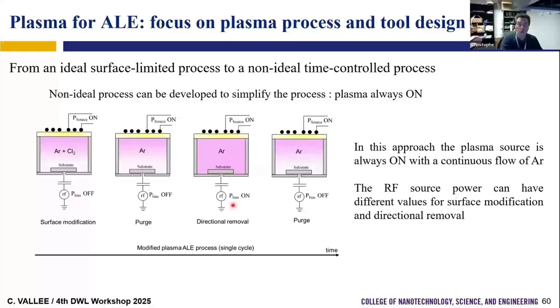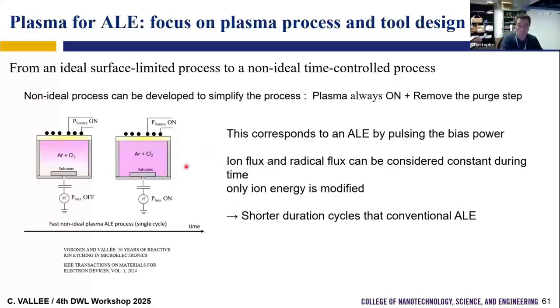But if we want to go faster, we can also simplify, and try to no longer pulse the chlorine, and only pulse the bias, and we play with the duty cycle to try to have an ALE-like process. It's more challenging because since at the same time we have chlorine and argon, we may have an RIE process, which is what we usually have with RIE. So you have to find an ideal duty cycle and an ideal frequency to not go to RIE, but to have a self-limited atomic layer process. But you can find some papers where people were successful in developing an ALE-like process by only pulsing the bias.